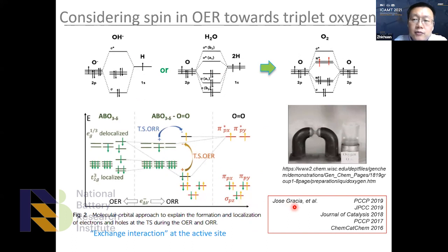And he has done very systematic modeling work. Basically, our opinion is that if we produce triplet oxygen, and we look at the precursor of this OER, which is either water or hydroxide ions, all the oxygen there is singlet oxygen. So in this case, the reactants and the products are not balanced. They are not magnetic-ordering balanced. They involve an additional energy barrier for the spin-selected electron transfer.